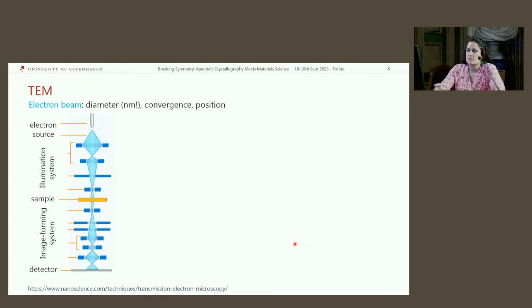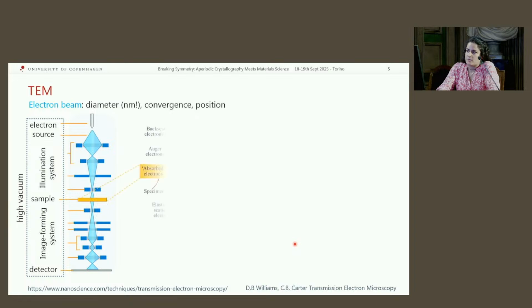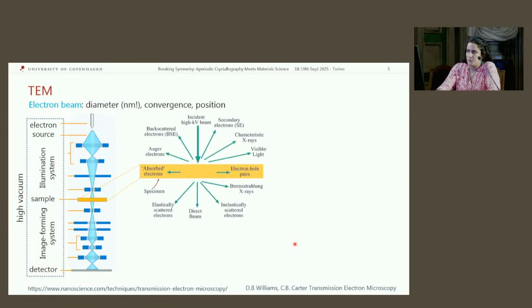So these crystals are too small for X-ray diffraction, but we can analyze them with the transmission electron microscope. So here we are using an electron beam that, because electrons are charged, with electromagnetic lenses we can precisely control the shape, the diameter, the focus, and even the position of the beam. On the other hand, electrons interact with everything, so this instrument is in high vacuum. And when we illuminate a sample with a beam of high-energy electrons, many interactions occur at the same time.